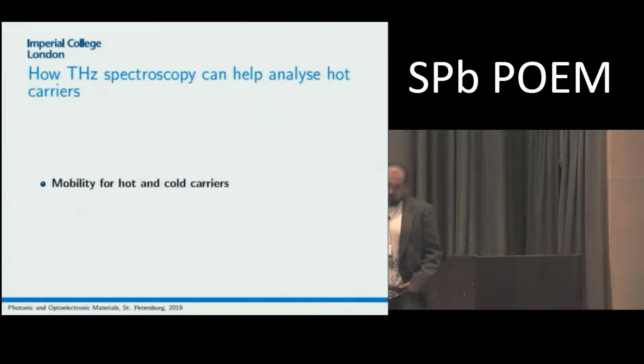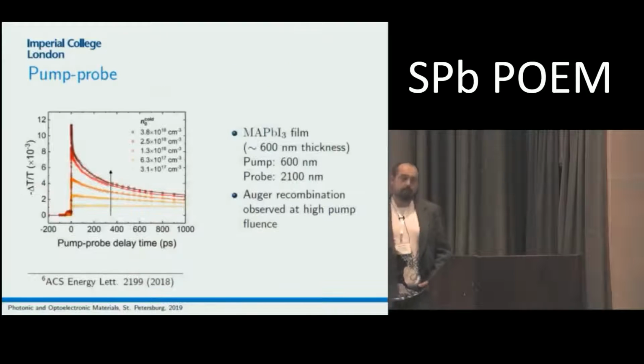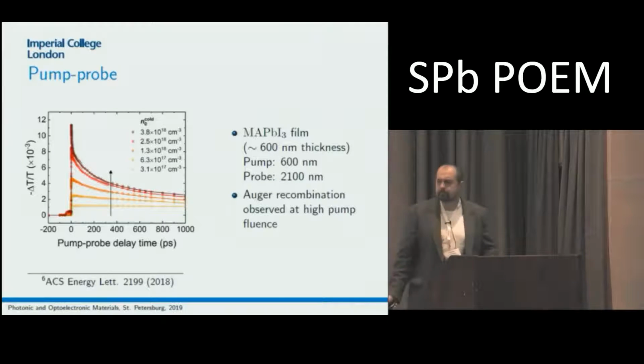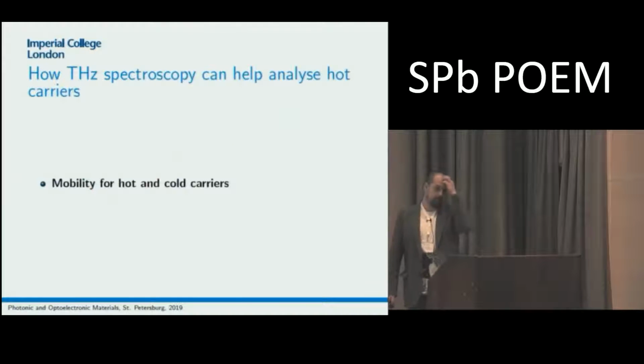But if we turn to terahertz transmission measurements in just a normal pump probe layout, normal infrared pump probes would measure carrier concentration only. But terahertz transmission will be related not only with carrier concentration, but also with carrier mobility. So by direct comparison of carrier concentration derived from pump probes and carrier mobilities in terahertz measurements, we can derive carrier mobilities at